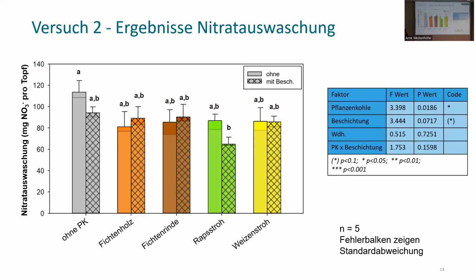What we see is that the use of biochar did have an effect. And the coating also contributed slightly, maybe. You see that there are differences depending on the feedstock you use. Nitrate leaching is higher with the coating as compared to without coating. The straw biochars, it's the other way around. I'm going to show it to you in a moment.